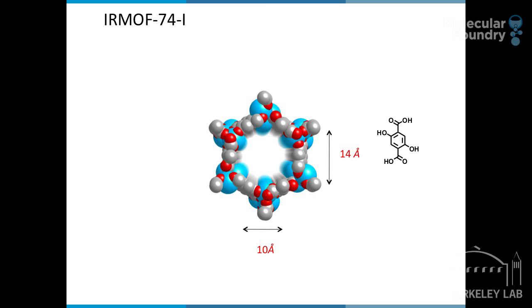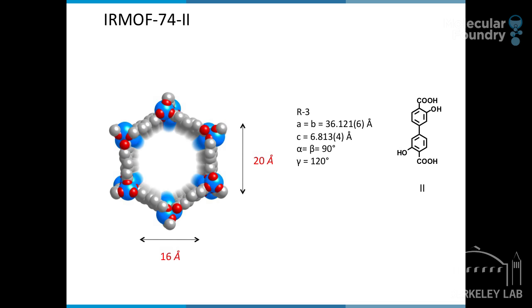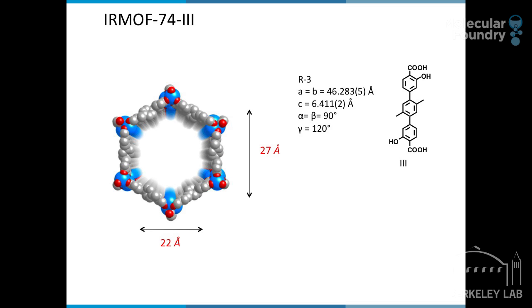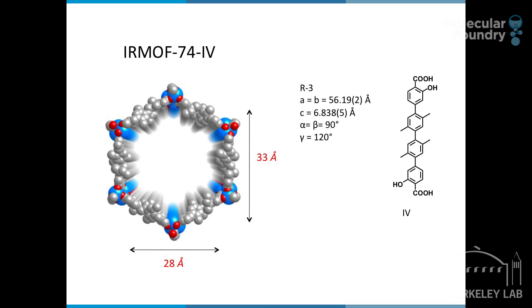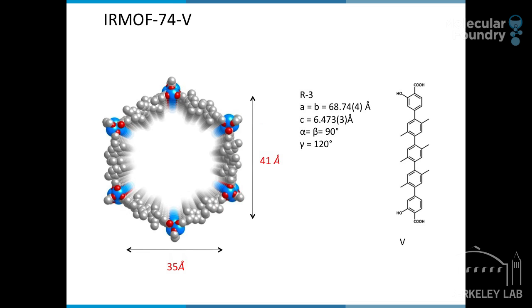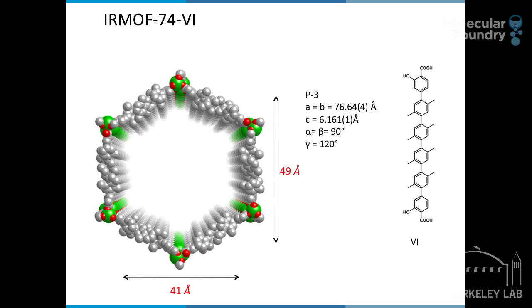This is the opening of MOF 74, the parent structure. And I'm indicating here the dimensions, 14 angstroms by 10 angstroms. And this is only with 1 phenylene unit. But my students made 2 phenylene units, the same structure, but now the pores are 20 by 16. 3 phenylene units gave us 27 by 22. Now we are approaching the world record, 33 by 28, 4 phenylene units, 5 phenylene units, and we went on to 6, 7.